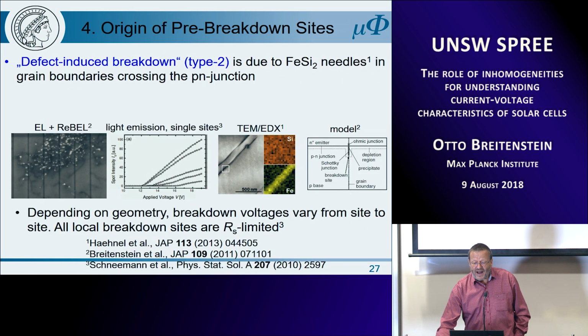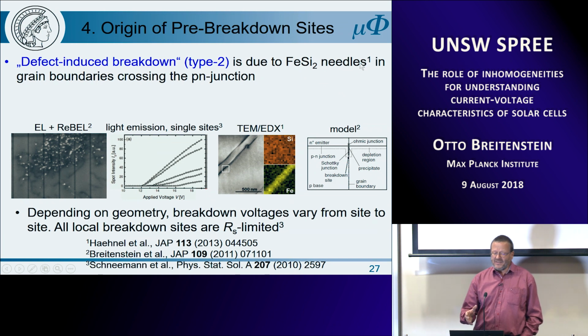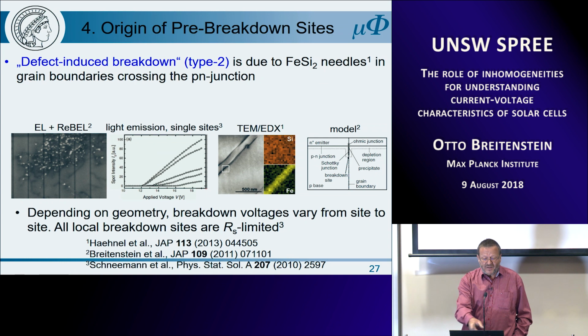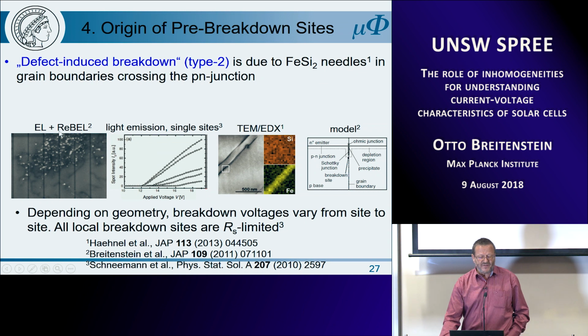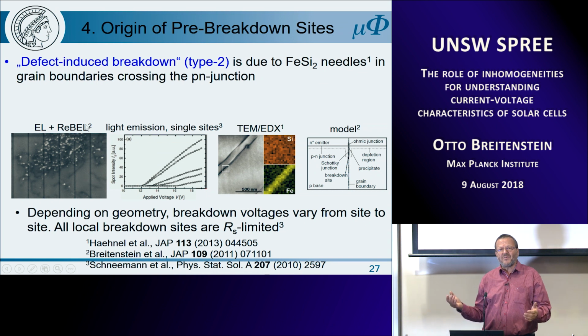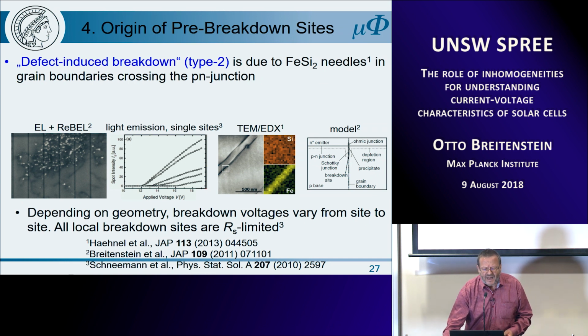And then type 2, it's very different. It is due to iron silicide needles, which we have found in grain boundaries crossing the pn-junction. And here we show the EL plus reverse bias, this means reverse bias electroluminescence. So in reverse bias, if we have some local breakdown sites, they show up as bright spots. And here they are superimposed to the dark lines coming from standard electroluminescence. And you see the breakdown sites are only in the position of these dark lines. So this has something to do with each other.